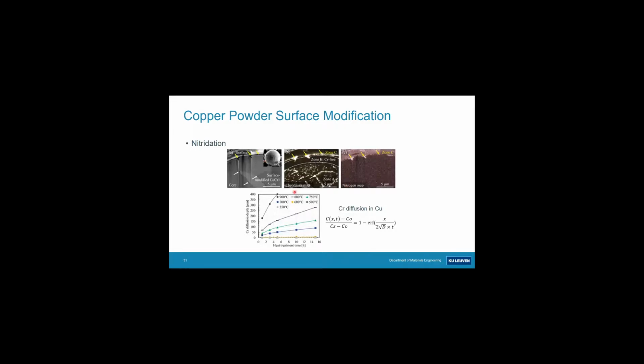Here you see a detail. So all the black dots here along these grain boundaries are chromium. You have a surface reaction layer, which is mainly chromium nitride, and this is the chromium depleted zone.